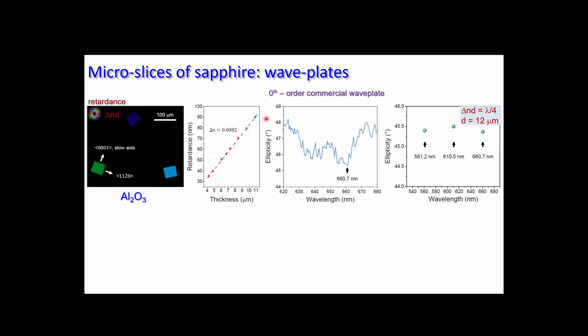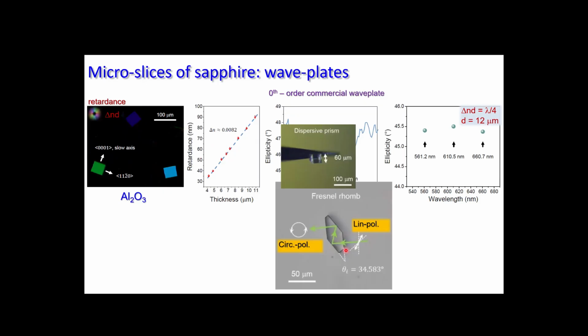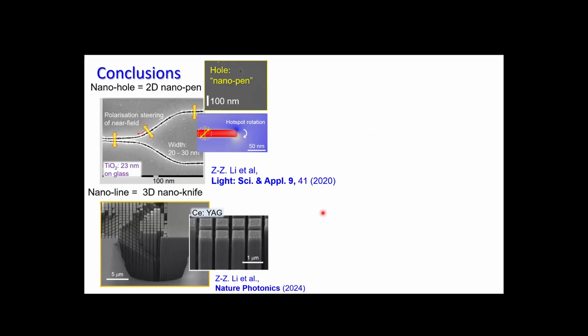And if you do this, from a birefringent material, which is sapphire, you can create quarter-wave plates, which make circular polarized light because you just cut the correct thickness of your film. And the same, you can cut any optical element from a slab of glass. For example, for the same function in 2 reflections, you have circular polarized light emerging from a Fresnel rhomb, and those surfaces are just laser irradiated and etched out. So this brings me to conclusions.